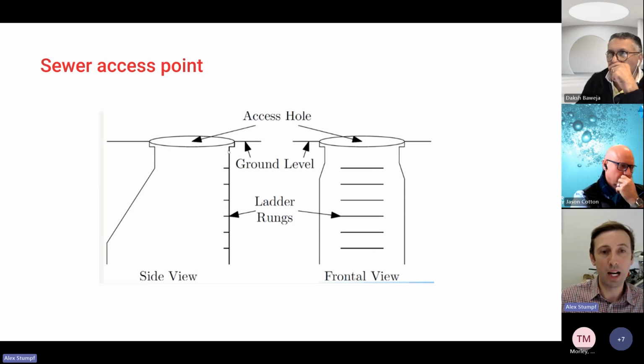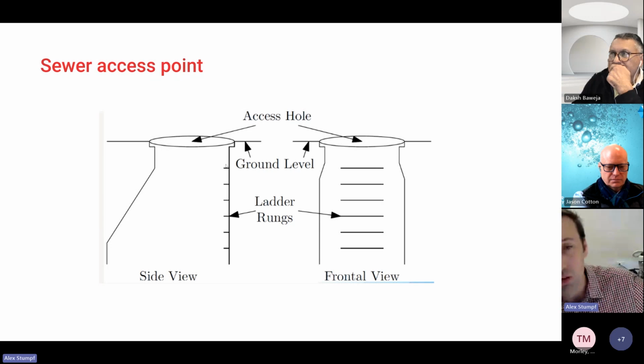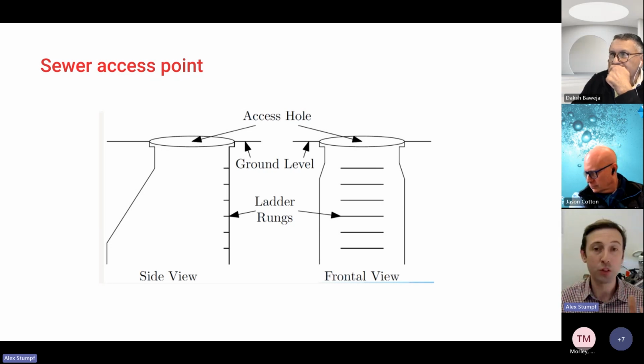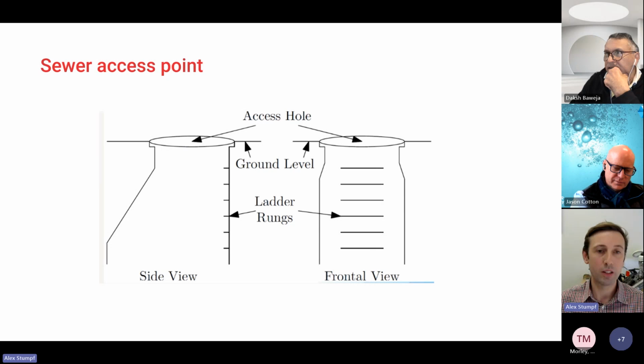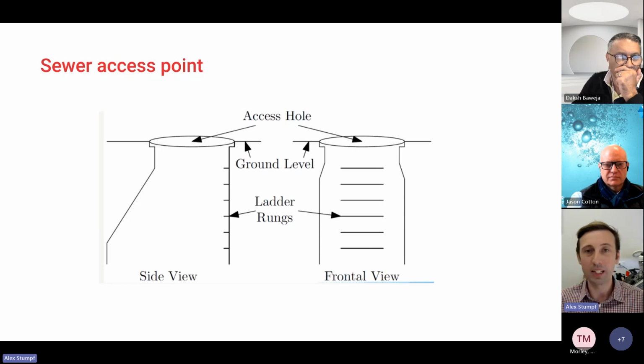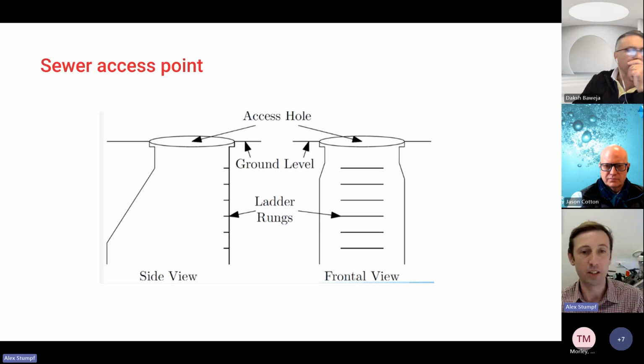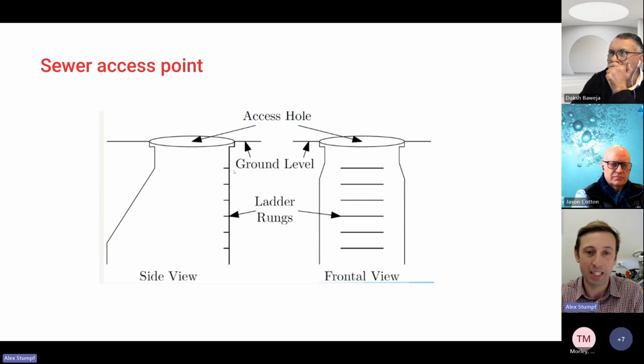In the hole, especially for the older pipes, we have ladder rungs. Depending on the water authorities, these have been removed. There are two schools of thought in terms of whether the ladder rungs need to be removed or not. If someone needs to go inside the pipe, one school of thought is that you could use the ladder rungs to get out in an emergency. The other school of thought is that these ladder rungs get in the way because you've got somebody harnessed up that they drop down into the hole. For us, because we're the robot guys, the ladder rungs can be problematic, especially if some of them come up into this 600 mil opening, which gives us less space to get the robot down into the pipe. So we would prefer if the ladder rungs were gone, but it is something that we need to deal with.